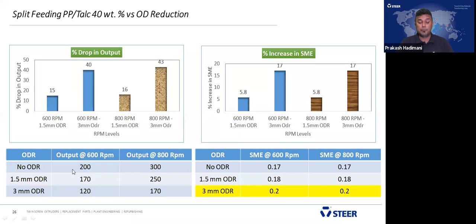That shows if your polymer is not 100% melted and mixed, there is a reduction in the throughput. With 1.5 millimeter OD reduction, 0.75 per side, at 600 RPM, there is a 15% drop in the output. At 600 RPM, if you do the 3 millimeter OD reduction, meaning 1.5 millimeter per side, a 40% drop in the output. At 800 RPM, similarly, with 1.5 millimeter, 16% drop, okay? And at 800 RPM, 3 millimeter OD reduction, both sides, 43% drop in the output.